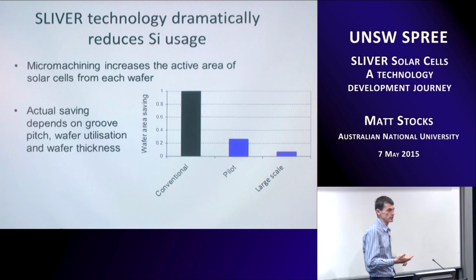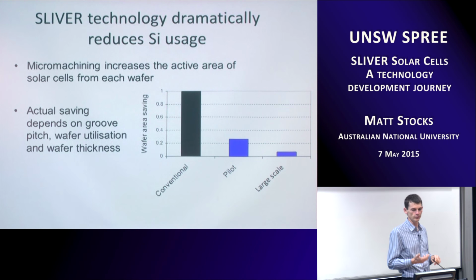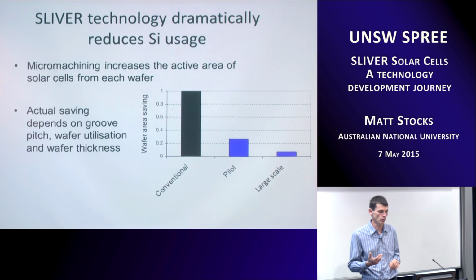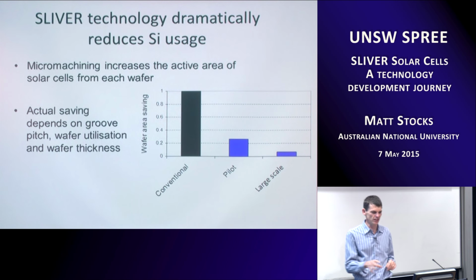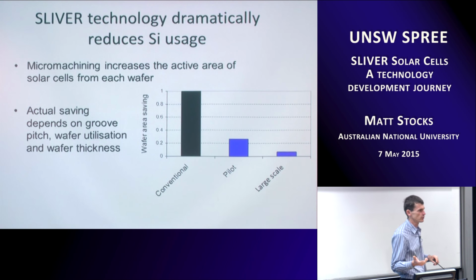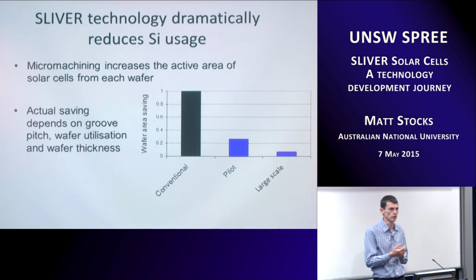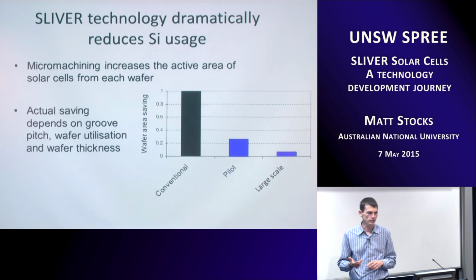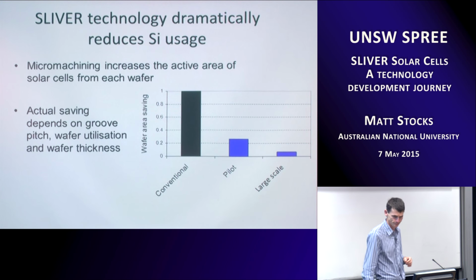So this was all originally about reducing silicon usage. So the focus was very much on how can we get our grams per watt down. This particular plot's in area, but another way of thinking about it is in grams per watt. The solar industry, when this was coming out, was looking at around about 7 to 10 grams per watt in terms of how much silicon was required in order to make a solar module. What we did when we were at the initial phases of this, we already had got things down to around about 2 grams per watt, and then by the end of the process we were getting down to less than 1 gram per watt. So it was all about originally focusing on silicon saving.